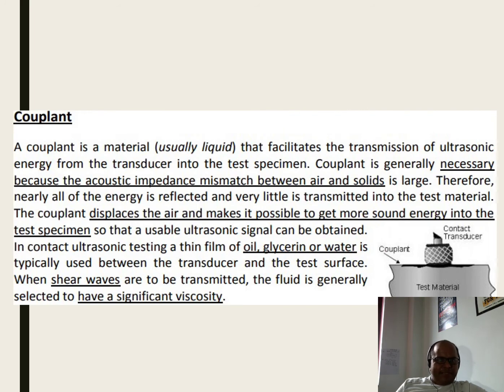What is couplant? Couplant is a material, usually liquid, that facilitates the transmission of ultrasonic energy from the transducer into the test specimen. Couplant is generally necessary because the acoustic impedance mismatch between air and solid is large. Therefore, nearly all the energy is reflected and very little is transmitted into the test material. The couplant displaces the air and makes it possible to get more sound energy into the test specimen so that a usable ultrasonic signal can be obtained in contact or immersion testing. A thin film of oil, glycerin or water is typically used between the transducer and the test surface. When shear waves are to be transmitted, the fluid is generally selected to have significant viscosity.